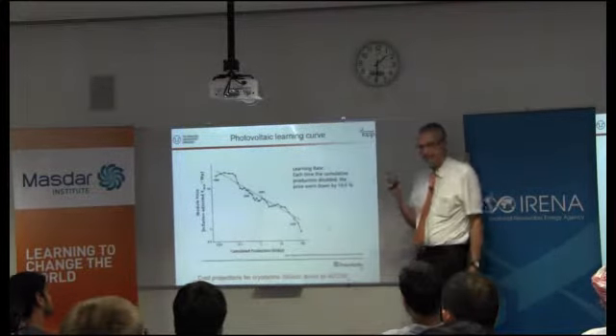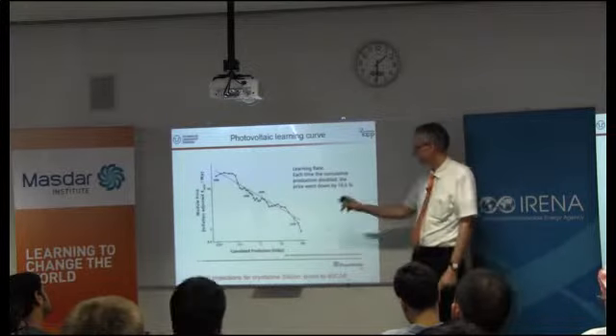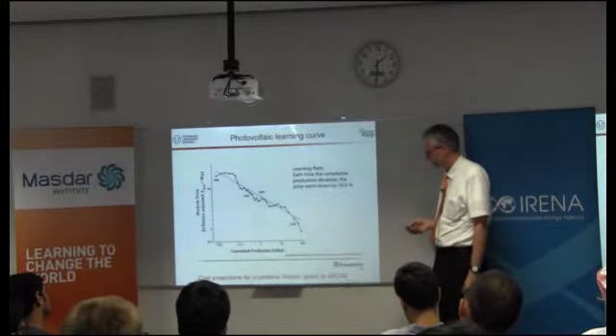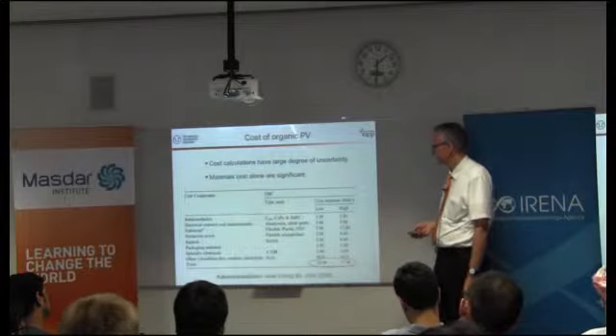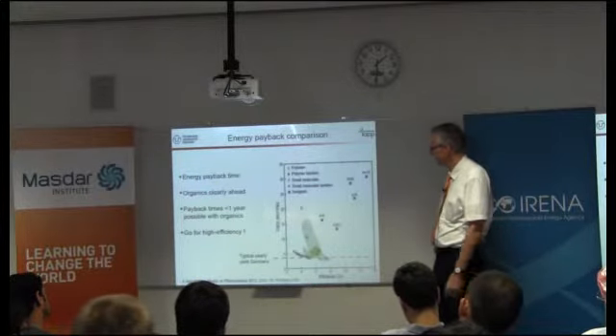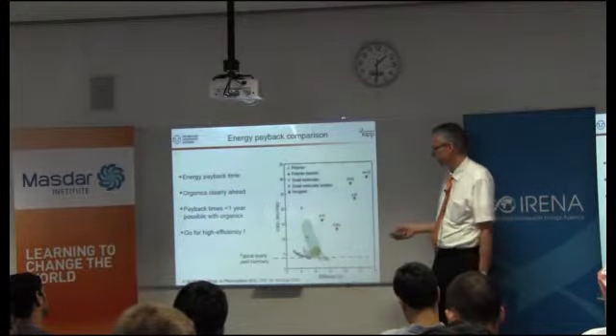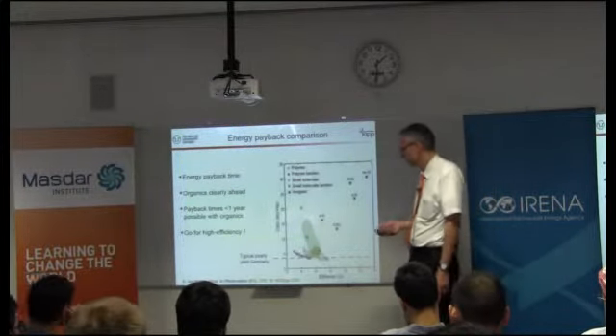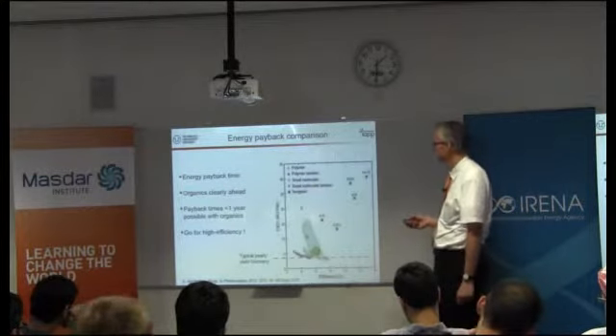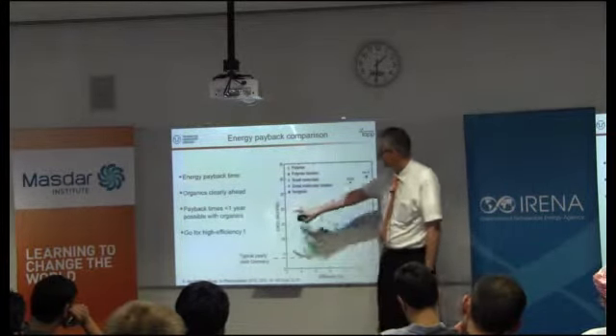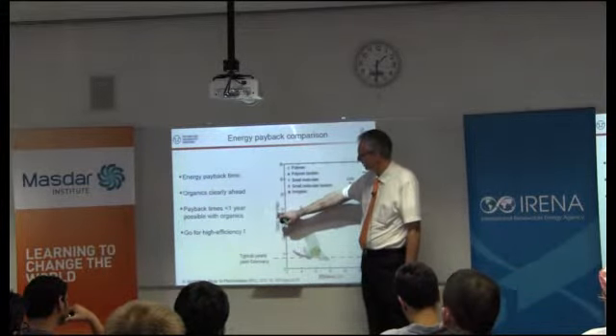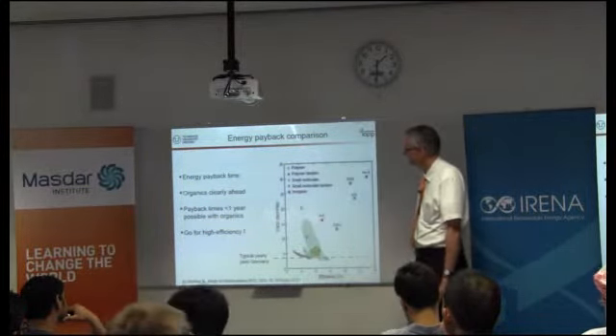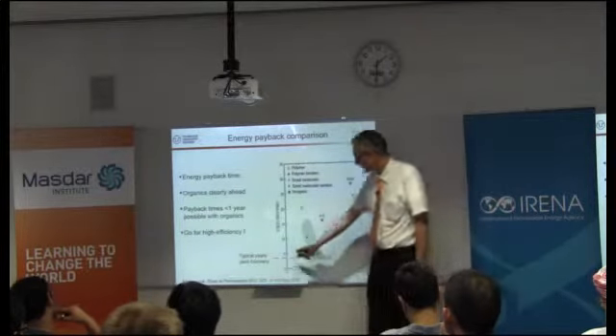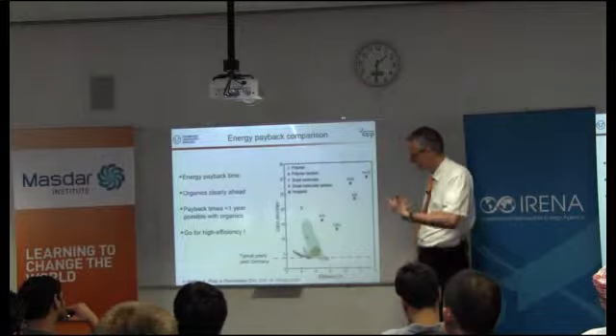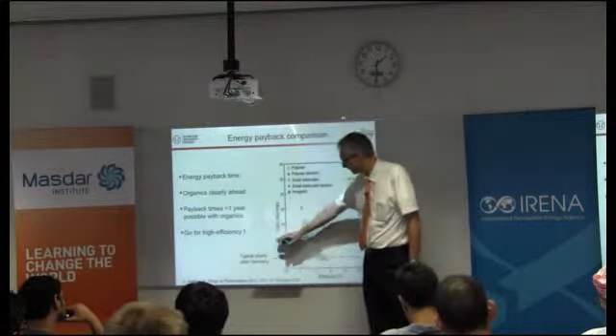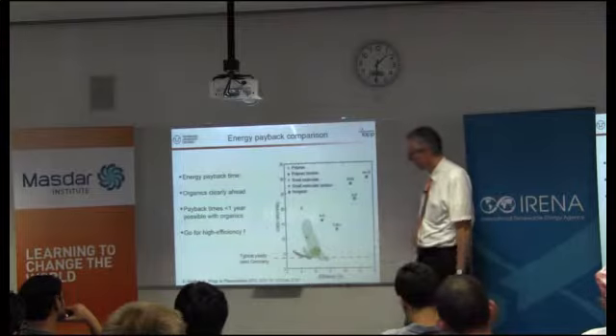So at least potentially, if we get high efficiency, organic PV can beat silicon, but the question is, can we get these high efficiencies? And the other point is energy payback, and this is a publication from Annick Anctil and collaborators who calculated energy payback. This is the amount of energy, megajoule per watt peak, you need. And I plotted here a dashed line, which is the harvest per year in Germany. In Abu Dhabi, you would definitely be a factor of 2 to 2.5 above it.